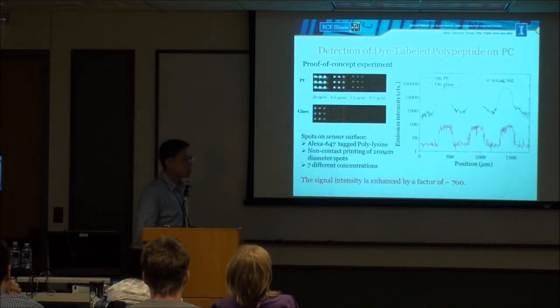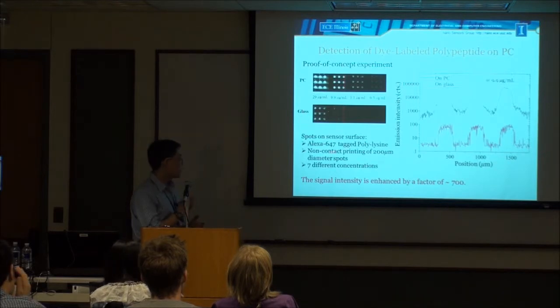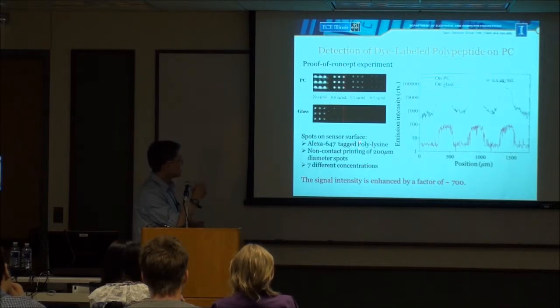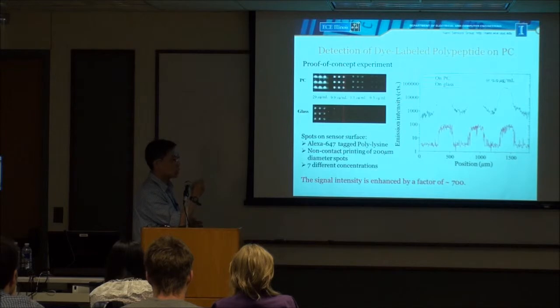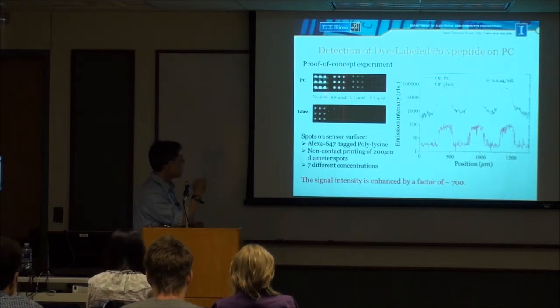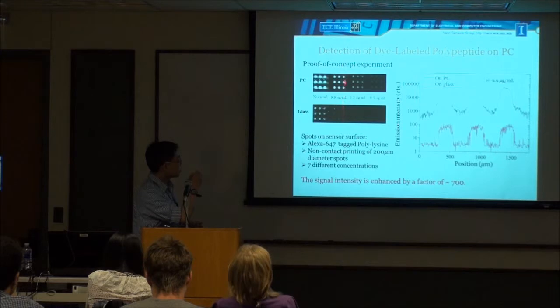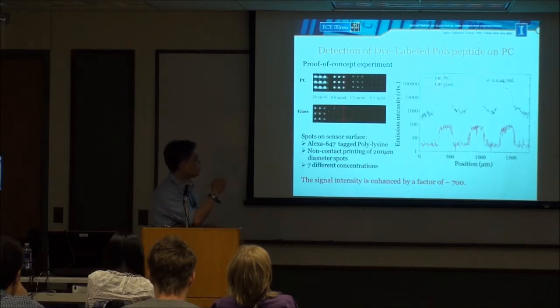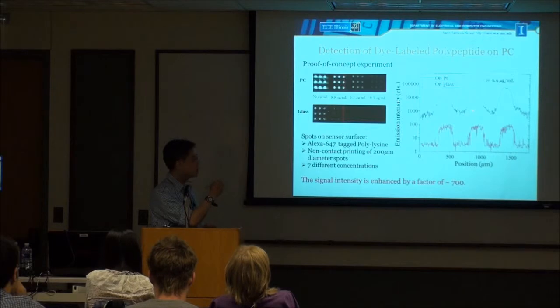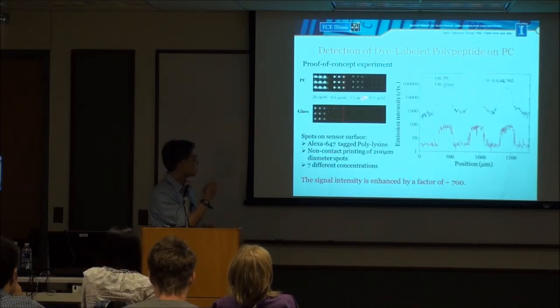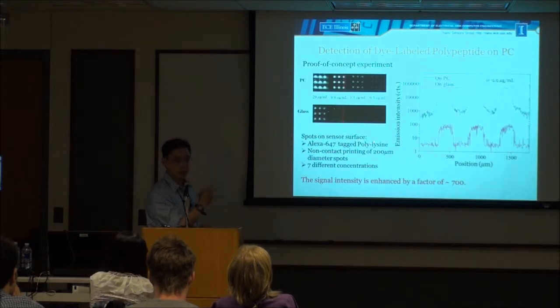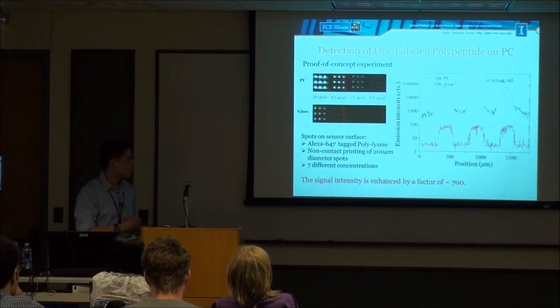As a proof of concept experiment, we use a simple dye-conjugated polypeptide. We spot an array of this dye-tagged polypeptide at 7 different concentrations, making a nice spot for each concentration, and measure the fluorescence emission image. As an example, we take a cross-section along the fluorescence image and plot the intensity profile in this figure. As you can see, on the photonic crystal surface, the fluorescence emission intensity is pretty strong, much stronger compared to the fluorescence intensity on a glass substrate. We calculate the enhancement factor to be around 700 times.